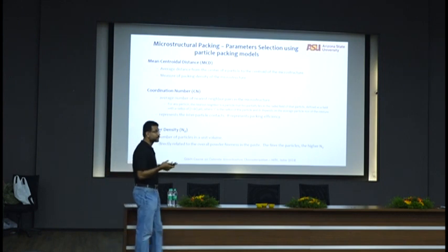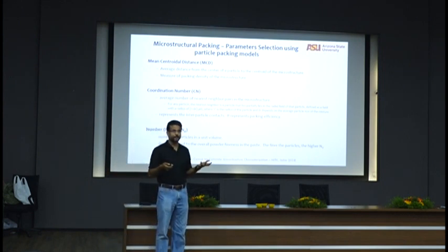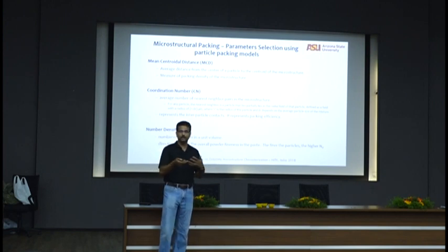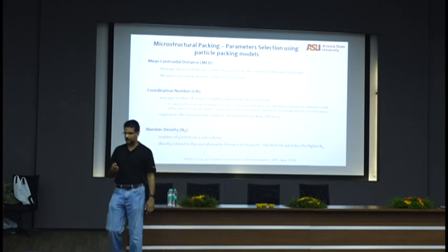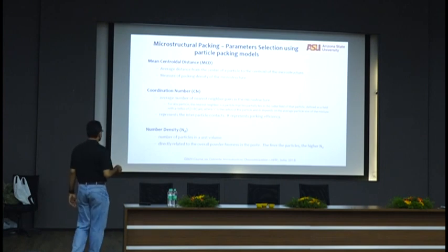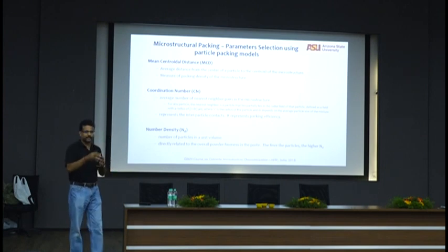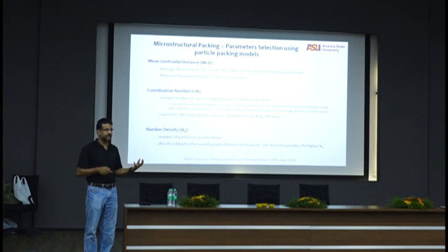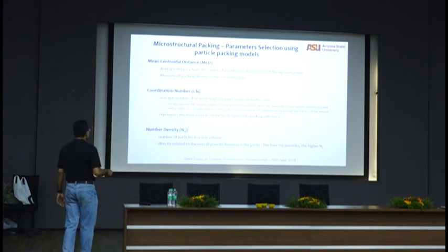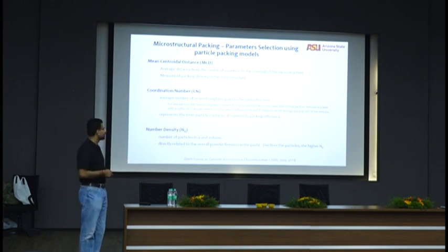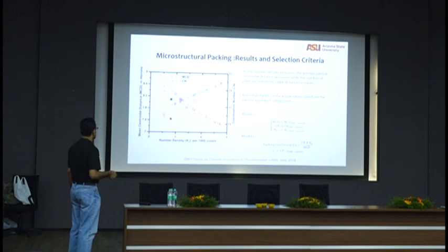Now, why is the distance between particles important? Because reactivity is governed by distance. The fly ash has to react with calcium hydroxide, so it has to have a certain proximity to react. The second one is coordination number: how many particles are touching any given particle at any given time? Again, a measure of reactivity. And the number density is the number of particles in a unit volume, which tells you how much filling you have. Then we came up with different models that relate centroidal distance, number density, and coordination number.